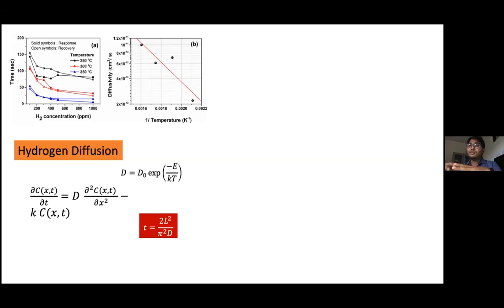It has more affinity towards the oxygen vacancies which are there, and it will bind with those present there and at the interstitial sites. Correspondingly, this is another donor, or some other defect, created as compared to the previous one. Some kind of equilibrium will take place between oxygen and hydrogen getting adsorbed, penetrating inside the lattice, equilibrating all over, and you are getting some kind of a saturation in your current measurement. So all these things are basically changing dynamically, and after a long time this happens.